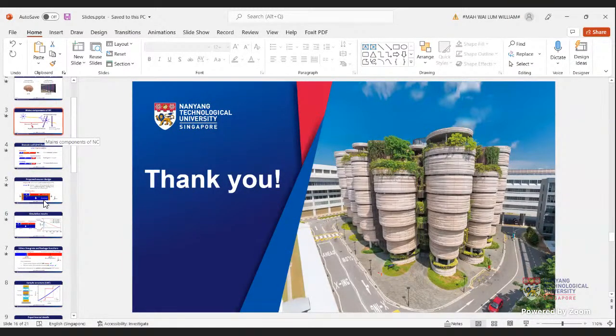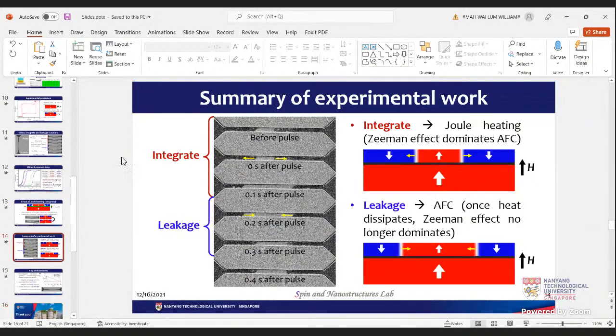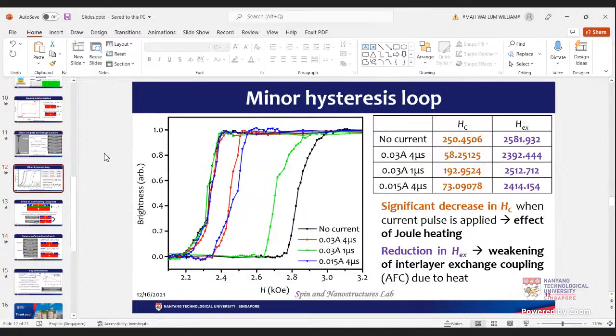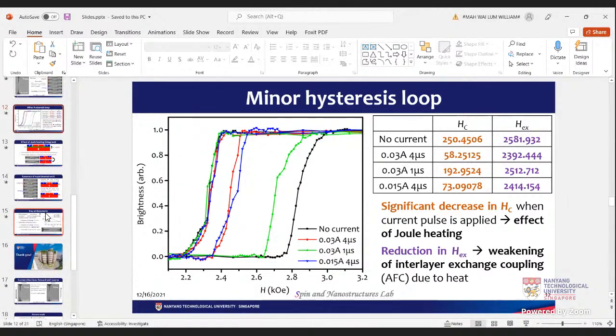So you're saying that the domain wall motion is primarily driven by Joule heating. If that is the case, if you use a smaller current, then the Joule heating should potentially be smaller. So do you observe that the domain wall moves slower in that case?